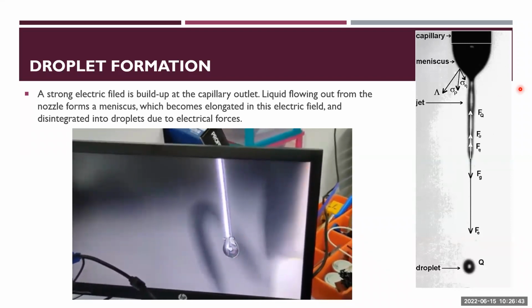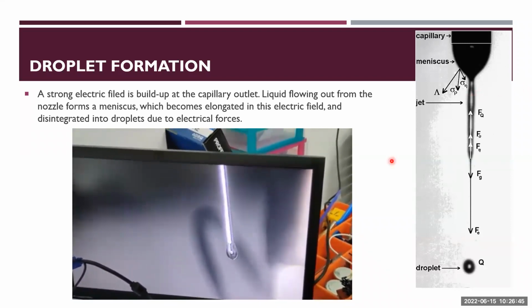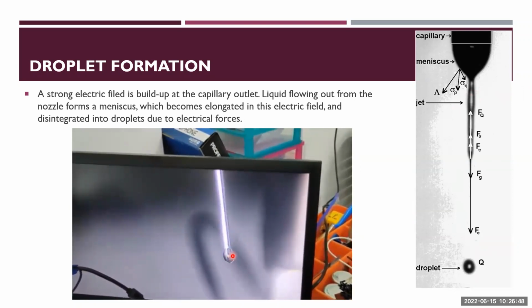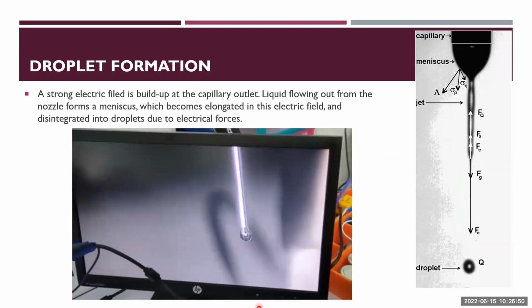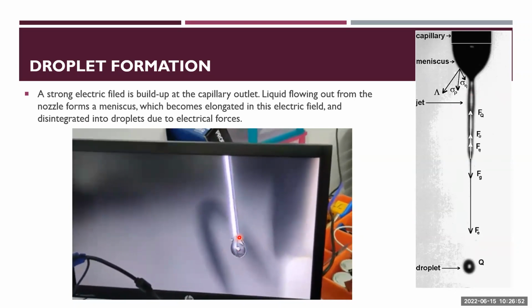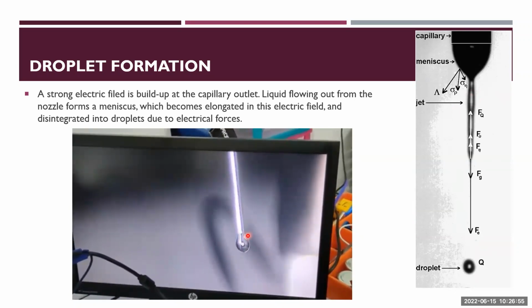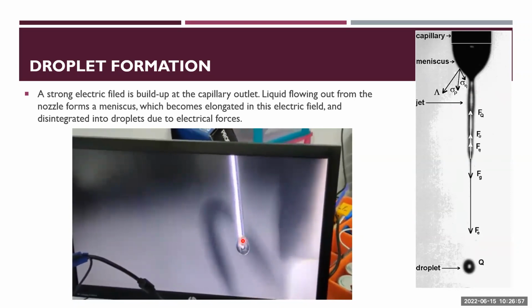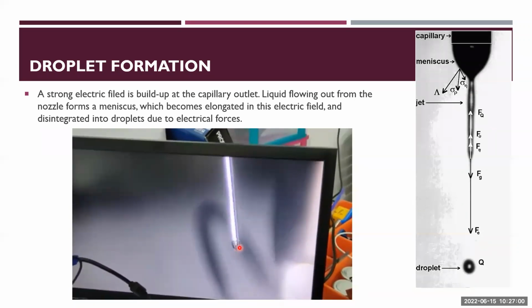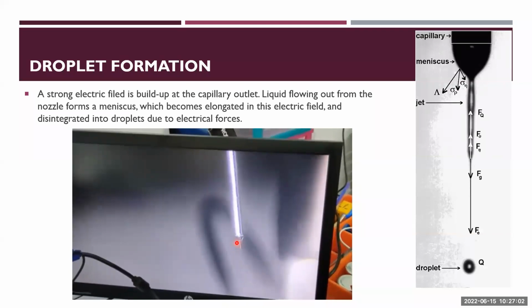But when we have an electrical field applied, the droplet becomes smaller, and there is some kind of force that pulls it down. By this way, the droplet size becomes smaller, and can even go smaller than the size of the capillary. You can see here I'm applying a stronger electrical field or high voltage. Then you can see the droplets get smaller and smaller, and finally become very fine particles, which in this one are in the size of micrometers.